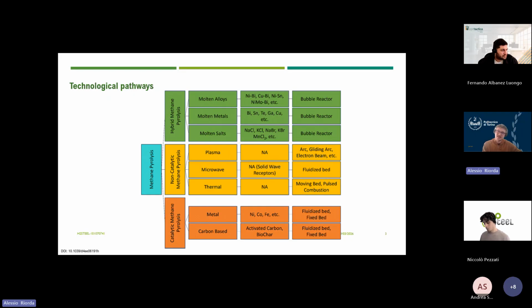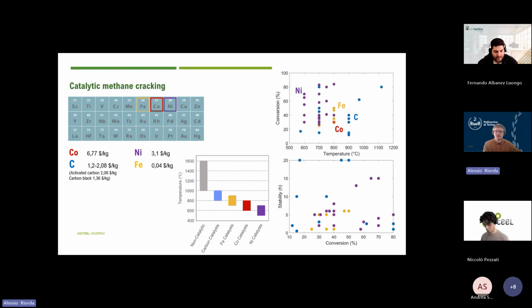Instead, if you want to use a catalytic process, you can use a catalyst to reduce the temperature needed for the cracking. In that case, you can use different kinds of catalysts, like metal catalysts, nickel, cobalt, iron, or a carbon-based catalyst, but we will see that later. Then there are also hybrid processes like molten metals or salts that have both actions, but these are not part of the presentation. Focusing on the catalytic cracking, as you can see here, you can have different metals.